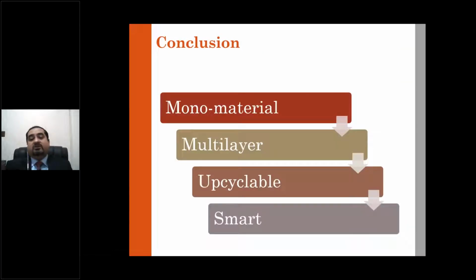So based upon these results, what we can conclude is that if we are able to use monomaterial, based upon the two case studies that we have just discussed, and if we are able to then combine the monomaterials with the various nanofillers added into them to produce multi-layered structures, those would then be upcyclable. Because of the presence of nanofillers, we have already established the fact that if you get good dispersion and distribution, and make sure you get good interaction between the polymer and the nanofiller, you will be able to get good upcyclable material.